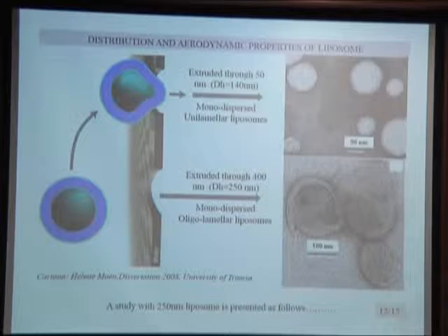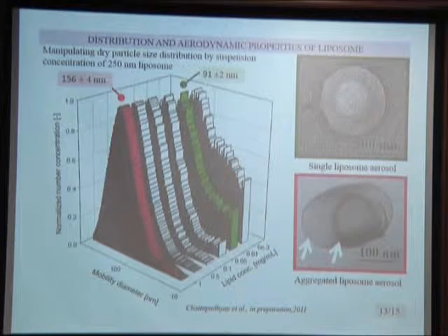We observed that the liposome size in suspension is about 140 nanometer, and again we extruded with 400 nanometer size, where we observed the liposome size in suspension is 250. These are flexible kind of particles, whereas this liposome has a different cladding of lipid layer. So you can see a multilamellar sort of structure. However, this is only a partial assurance that this is a multilamellar structure. We have other techniques which we are employing at present to confirm which are multilamellar and which are unilamellar structures.